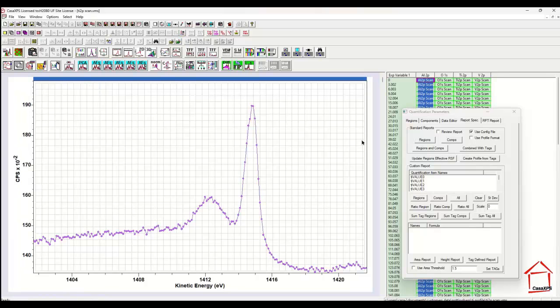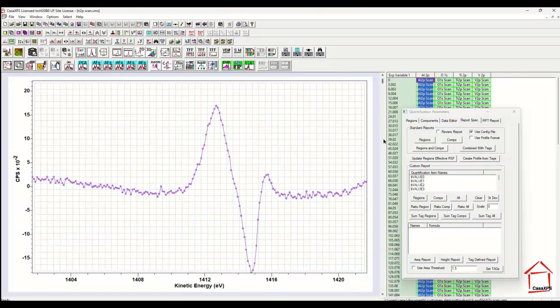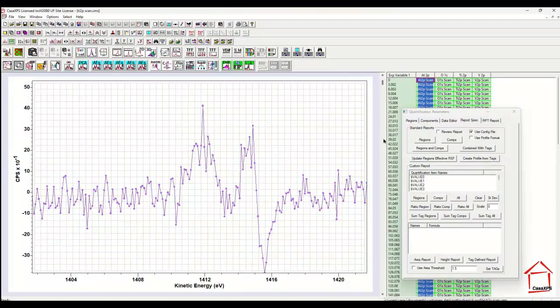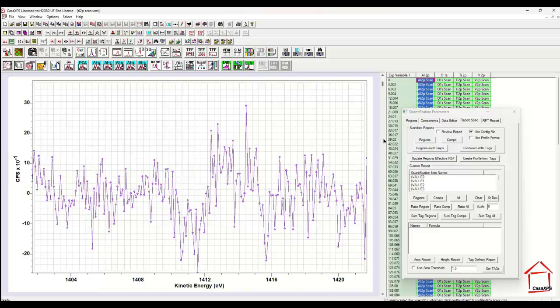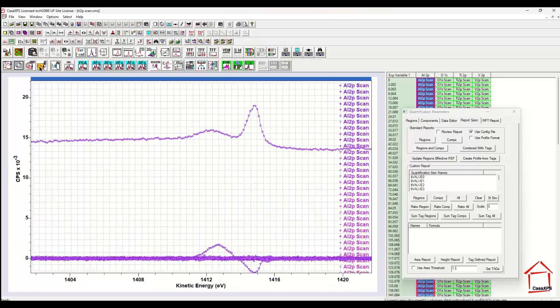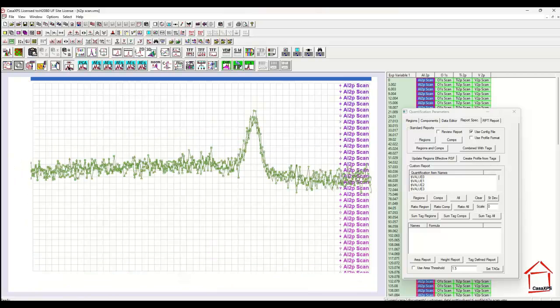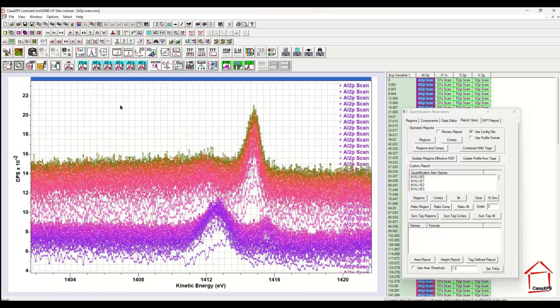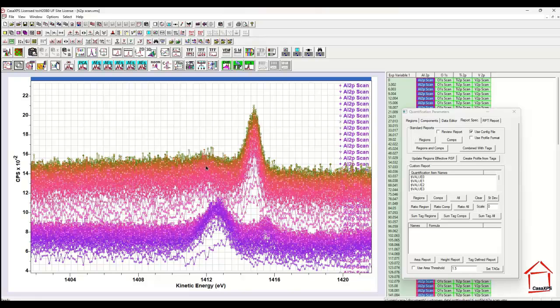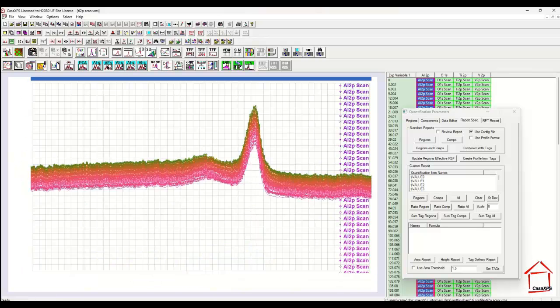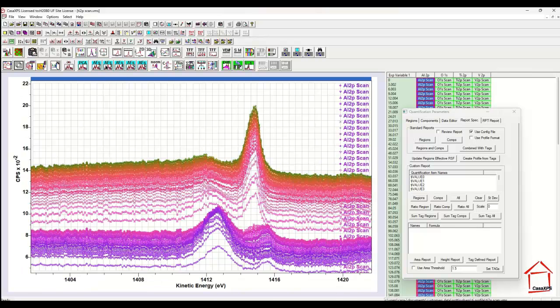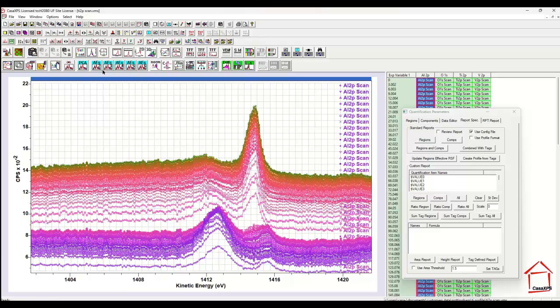And if I look at the number of abstract factors, I see there are potentially three abstract factors that would be useful for describing the signal in the aluminium spectra. So if I overlay these spectra again and reset, we see what the signal looks like before any processing. And if I choose three abstract factors to reproduce the data, then we see much cleaner spectra.